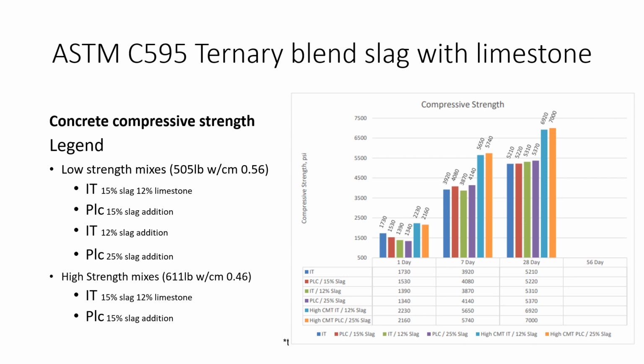to then do it. Drying it, obviously, is going to raise the impacts of it, right? So we don't dry it, but we can put it into the mill the same as we're putting in the clinker at the same time, and we can do it at 15% and not have to use the dryer.